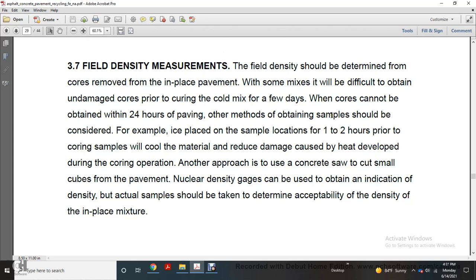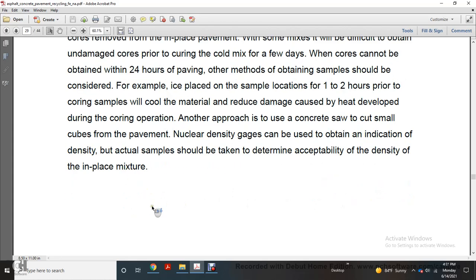One is to place ice on the sample locations, 1 to 2 hours prior to the coring. Samples of cold material reduce the damage caused by the heat development during the coring operation. Another approach is to use the concrete saw to cut small cubes of the pavement. The nuclear density gauge can be used to obtain an indication of the density, but actual samples should be taken to determine acceptability of the density in the placed mixture.